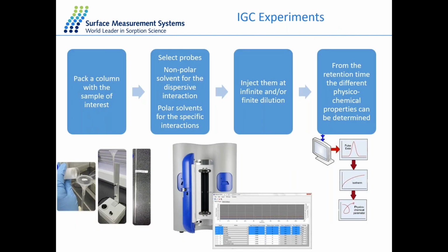So the procedure of performing an IGC experiment, we first need to pack the sample of interest into the column, like a glass column in the front here. And then we need to select different probe molecules for different interactions. So we need to select at least 3 different alkanes for the dispersive interaction and some polar solvent for the specific interactions. When we have the probe molecule, we can then inject them at different concentrations. And from all different peaks of the retention times, we can then calculate the physicochemical properties of the solid material we pack into the column here.